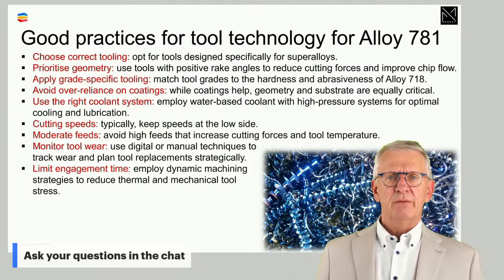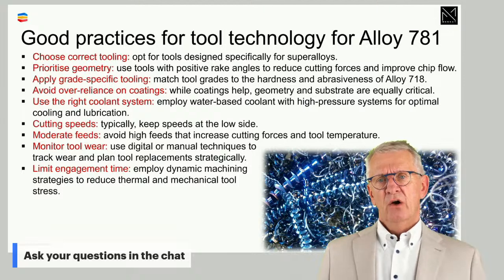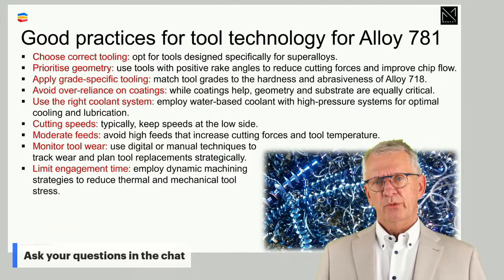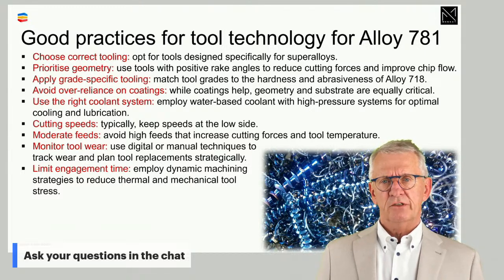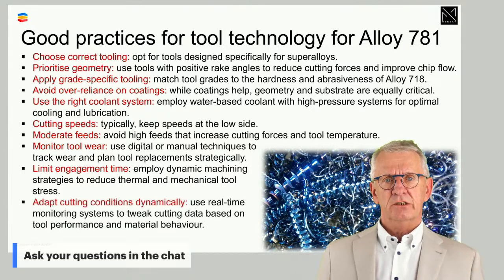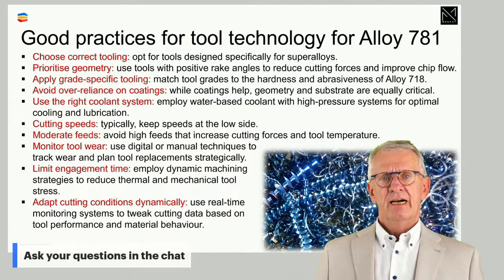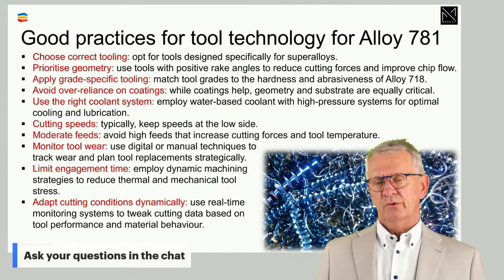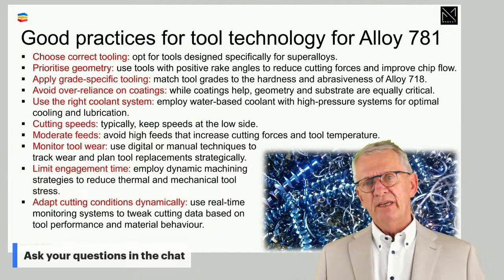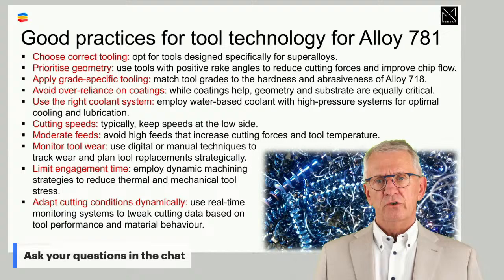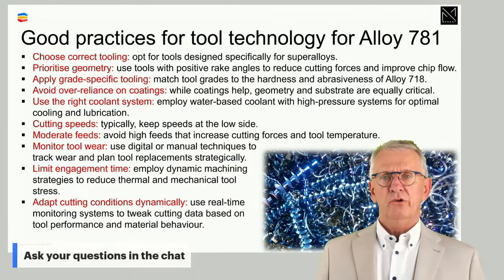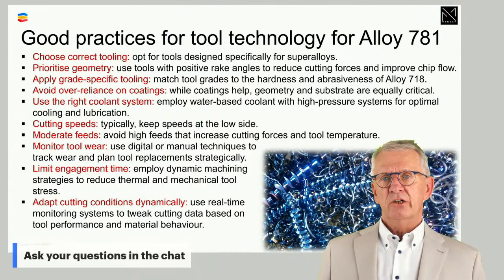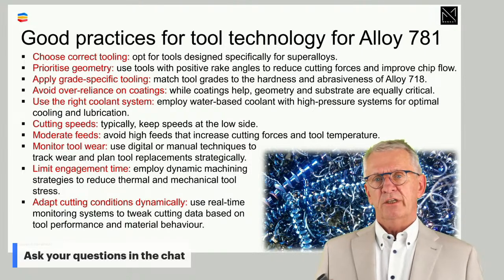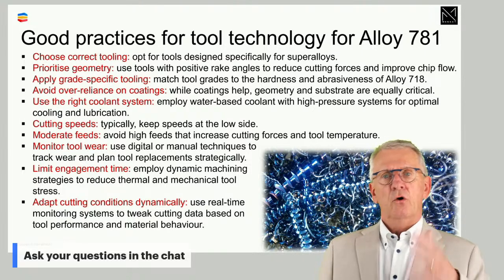Limit engagement time, especially in situations where you do not really cut, but you rub material. So too small feeds, too small depths of cut. Threading, again, is a very dangerous operation here. And there, where possible, modify your cutting conditions in a dynamic way. Depending on where you are during the operation, perhaps you should modify your cutting conditions. A milling cutter in a corner should be used with other cutting conditions than a milling cutter along a wall.